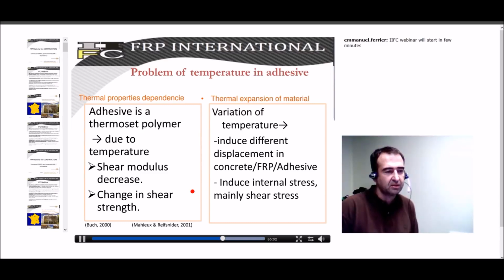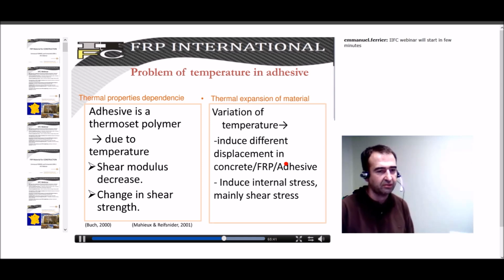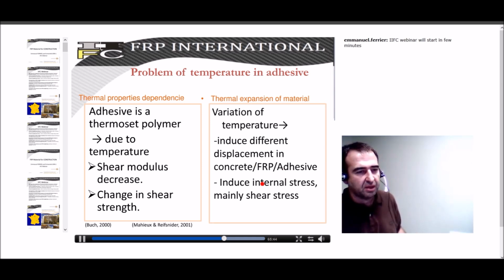So the problem that we found is that temperature dependency is quite important when we look at the problem of creep. And more recently, 2 years ago, we started to combine the problem of thermal properties dependency and the problem of loading. It means that the adhesive is sensitive to temperature. Shear modulus decreases and there is a change in shear strength. Due to change in temperature, that can also induce displacements between concrete, FRP and adhesive, because all those materials don't have the same thermal expansion factor. And this may induce internal stresses and some additional shear stress that have not been studied.